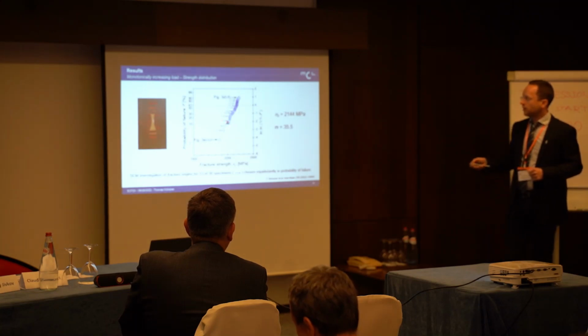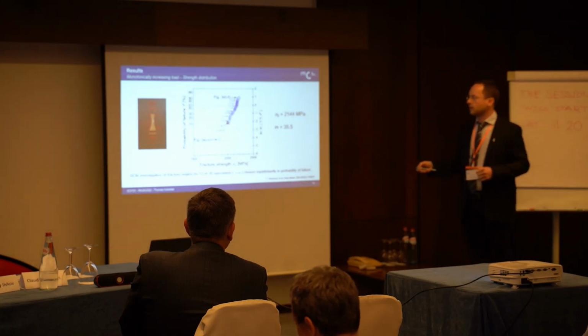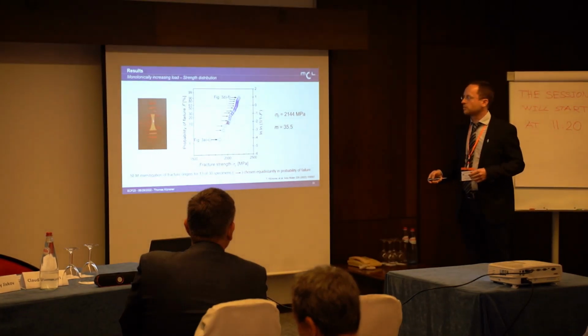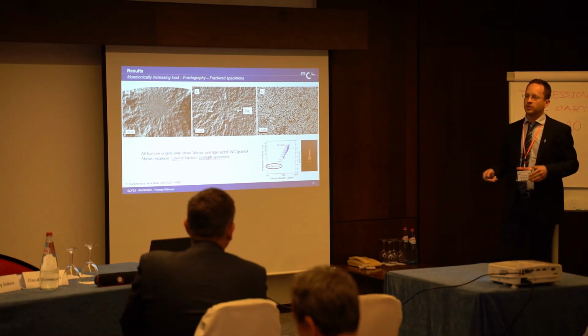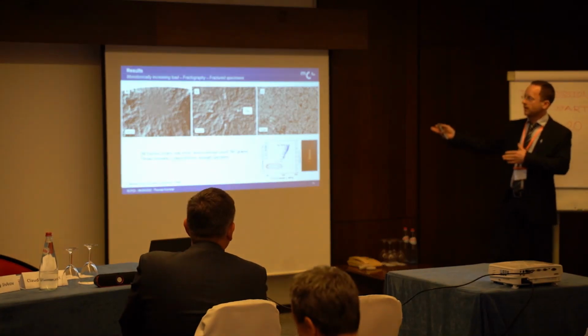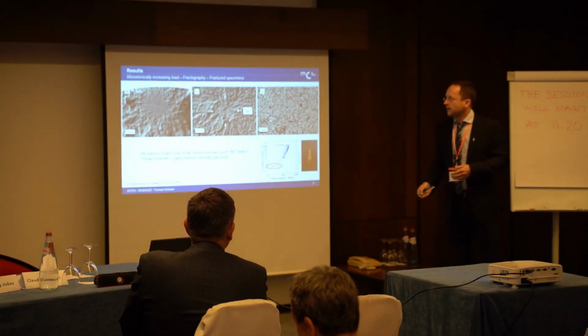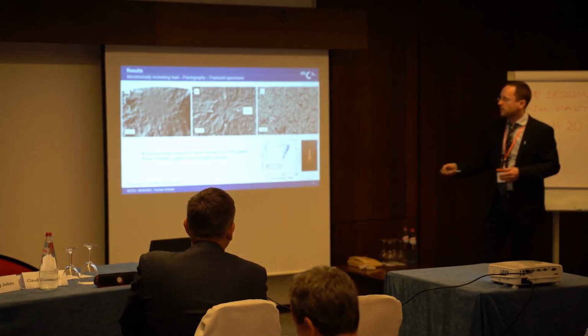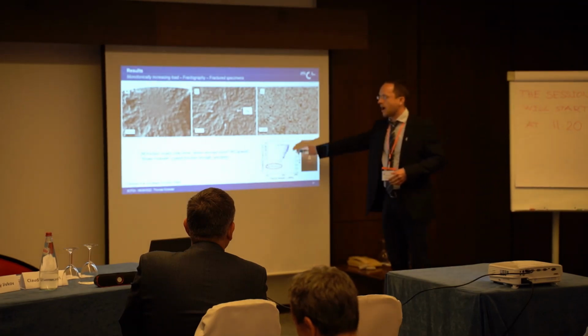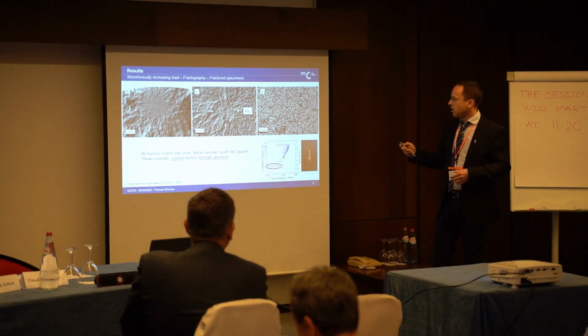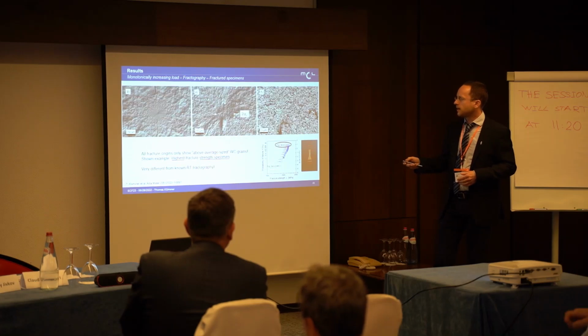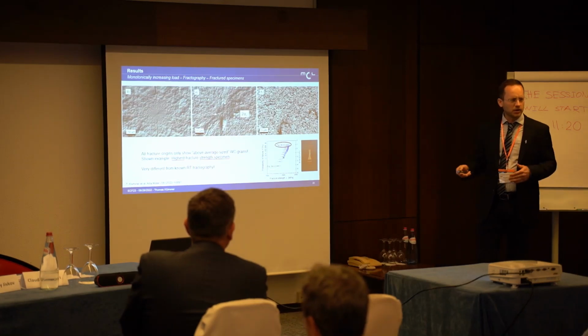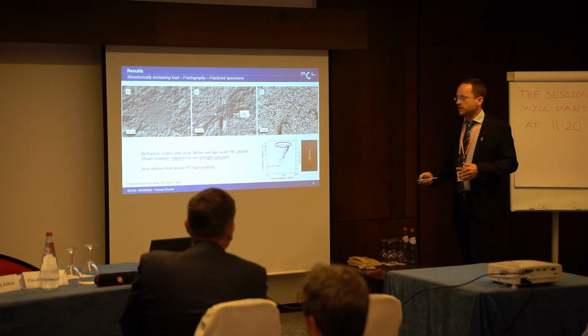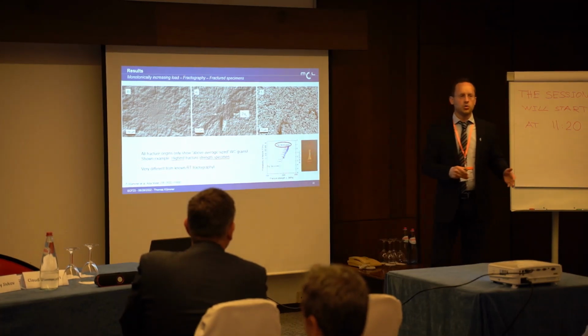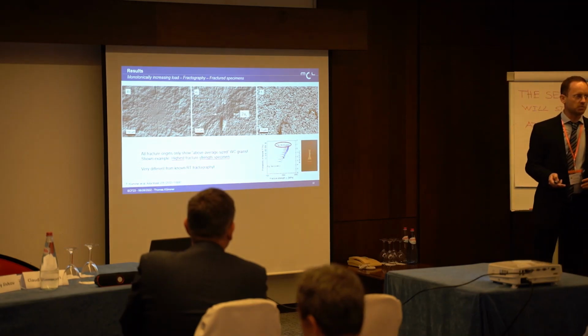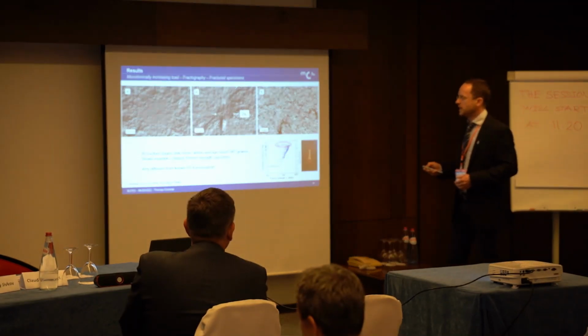And we looked at one of the microstructures that was loaded until a probability of failure of 10%, a fictitious probability of failure, and looked at what we see in the microstructure to find out maybe why we see what we see here. Because the fractured specimens, from the lowest fracture strength specimen to the highest, I'll show you examples. We see only above average sized tungsten carbide grains, which is very unusual for this class of materials, because usually for these large specimens you find non-metallic inclusions at the origin of fracture. So this was baffling, and we thought, well, what can be the reason for this?